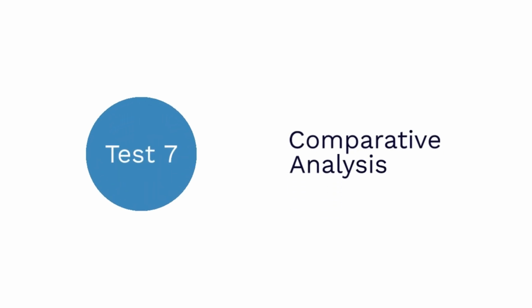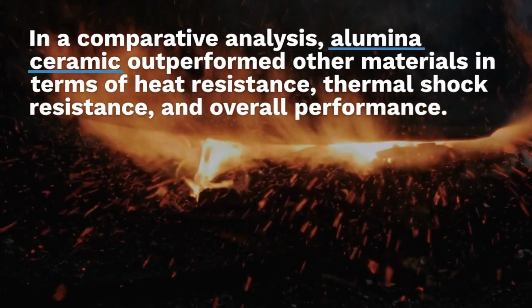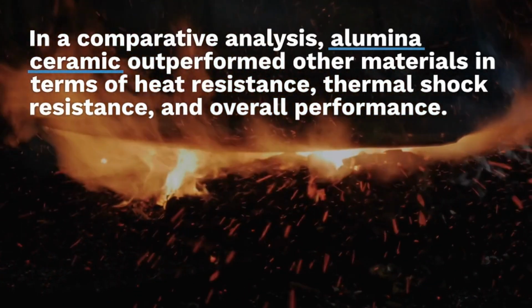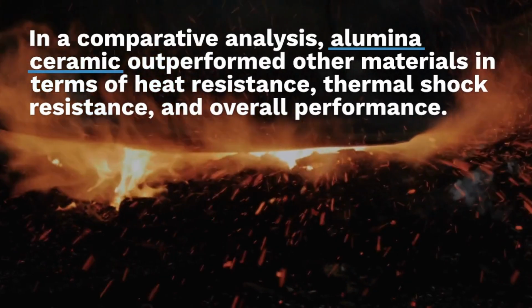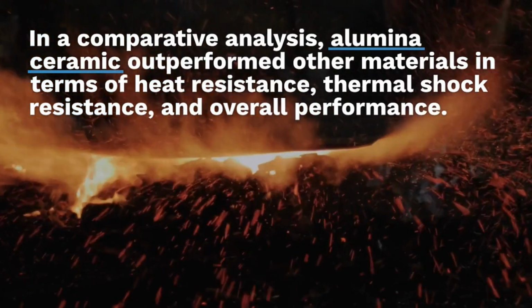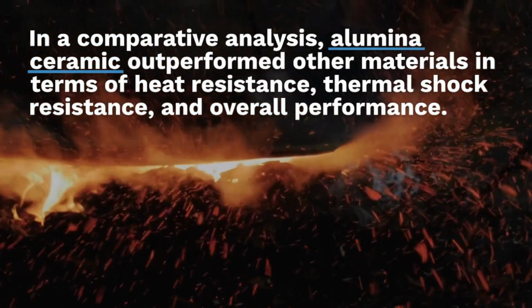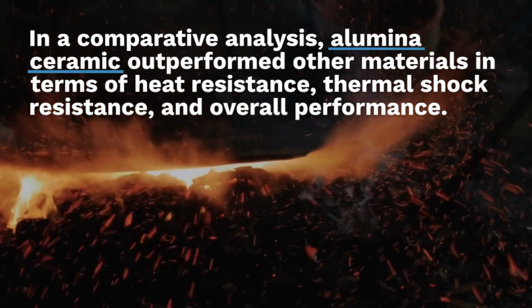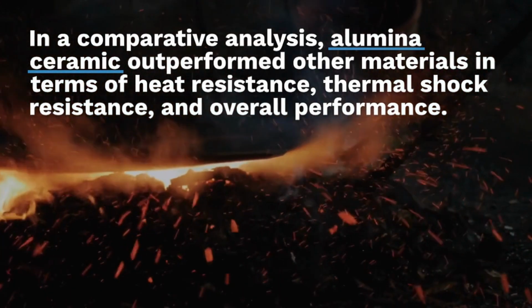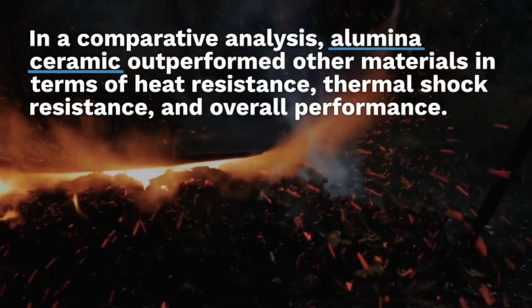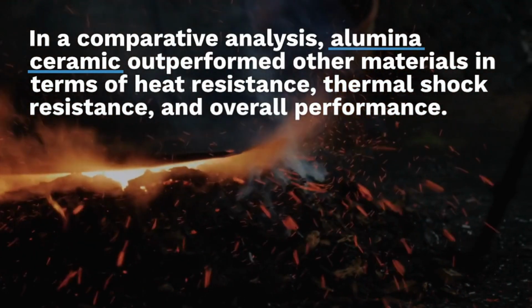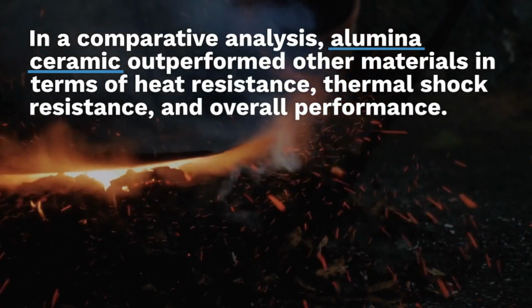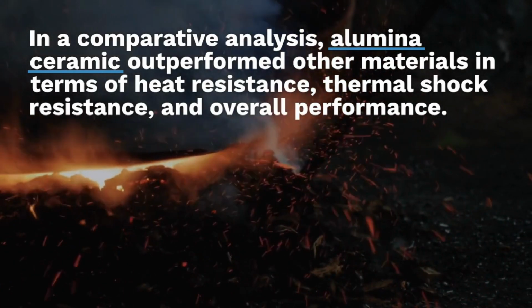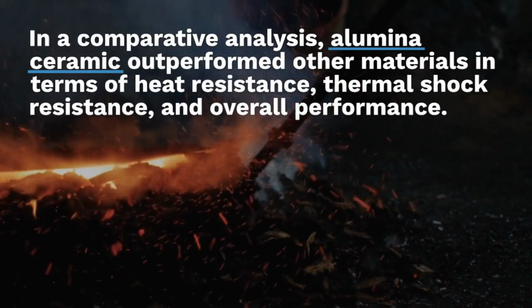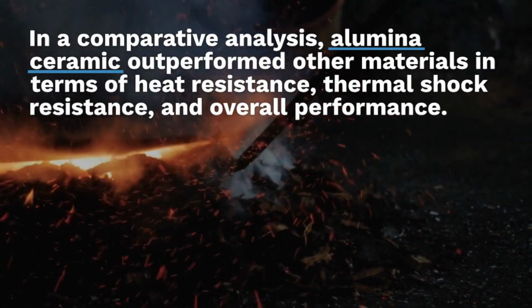In a comparative analysis, alumina ceramic furnace tubes were pitted against other commonly used materials in high-temperature applications, such as stainless steel and refractory bricks. The results unequivocally favored alumina ceramic in terms of heat resistance, thermal shock resistance, and overall performance. This analysis serves as a testament to alumina ceramic's superiority in extreme temperature environments.